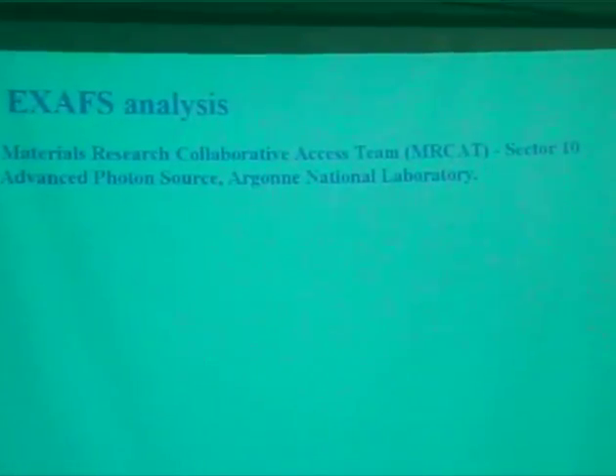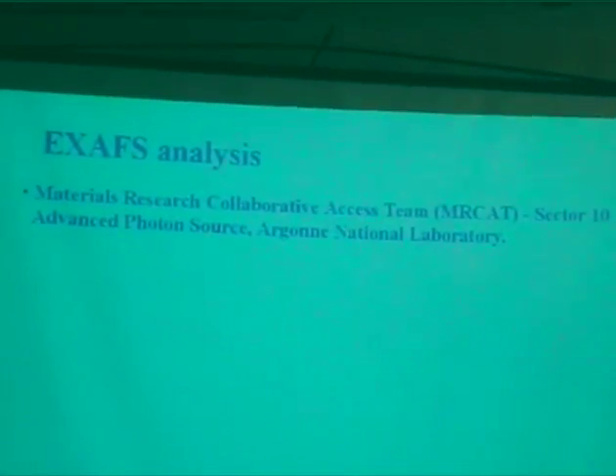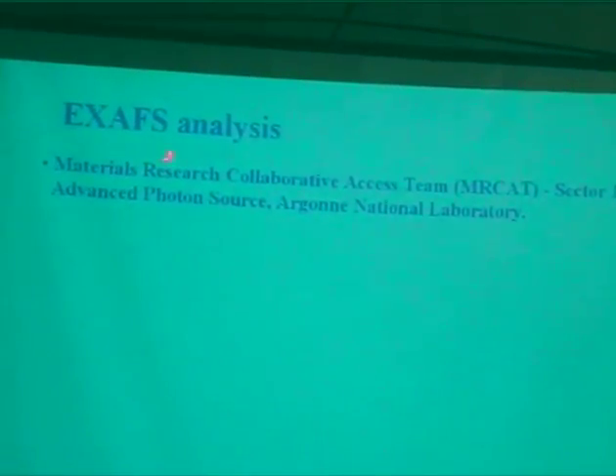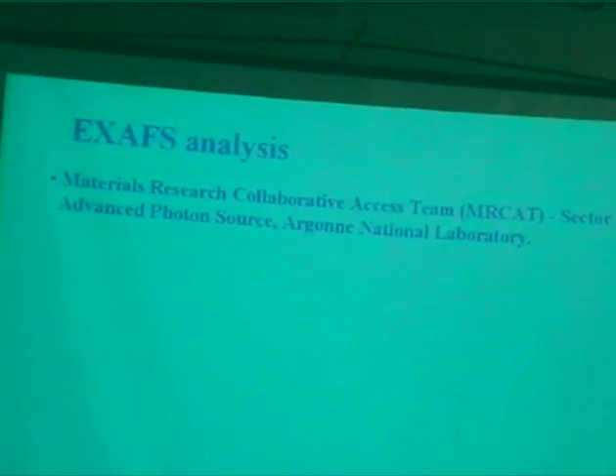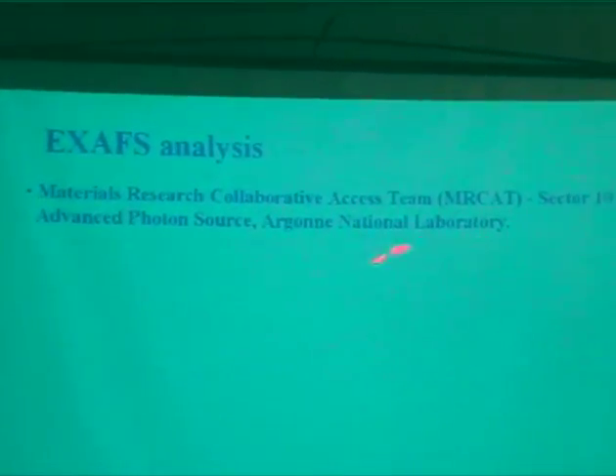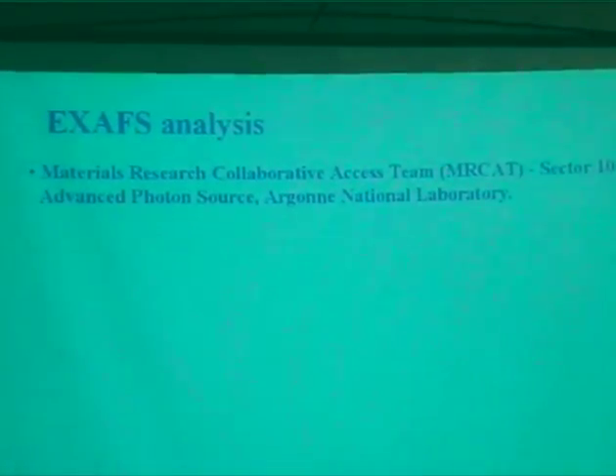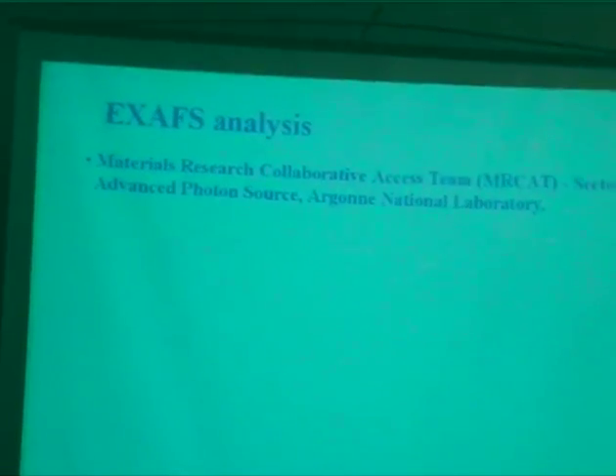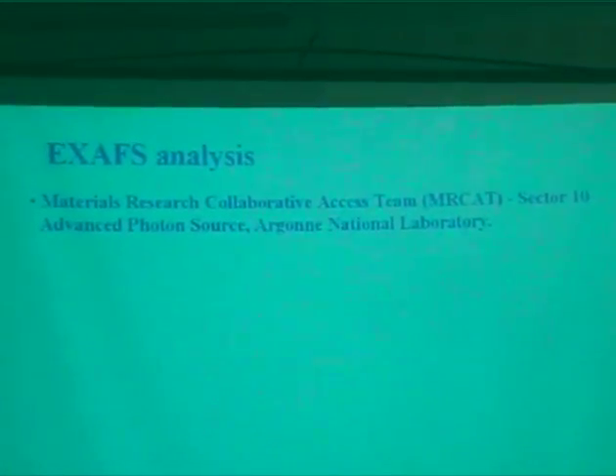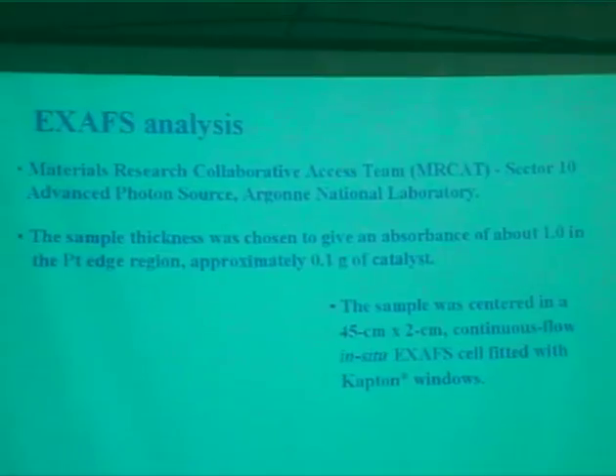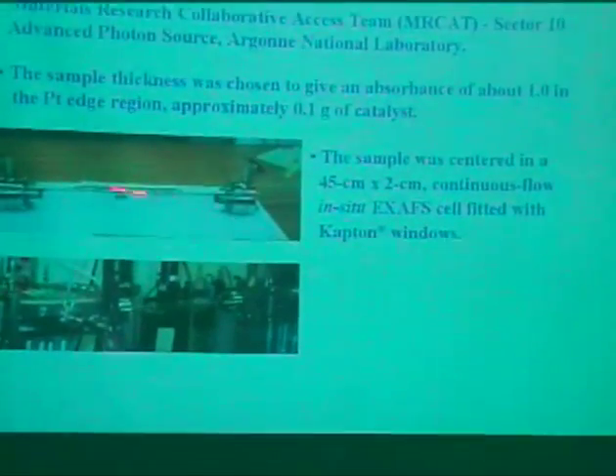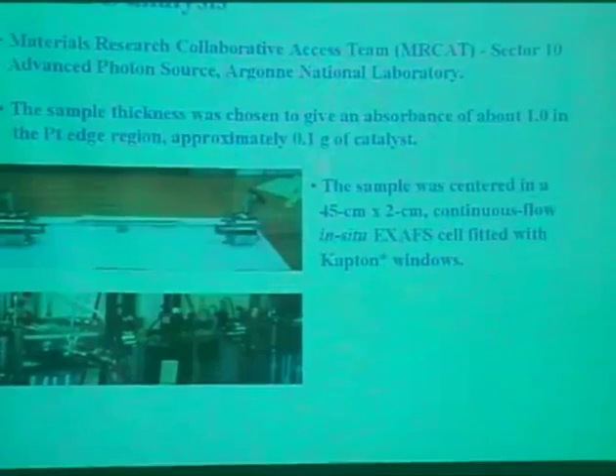Now this is what we normally do in our lab, the reaction part. This is where the collaboration with Jeff Miller and Jeremy Kropf came out. Argonne National Lab put together this fantastic facility with very high intensity X-ray synchrotron radiation. The main advantage of this is that we can do this at room temperature. Okay? And these are conditions that we use. And this is the important part. We do this, I would say, quasi in situ.